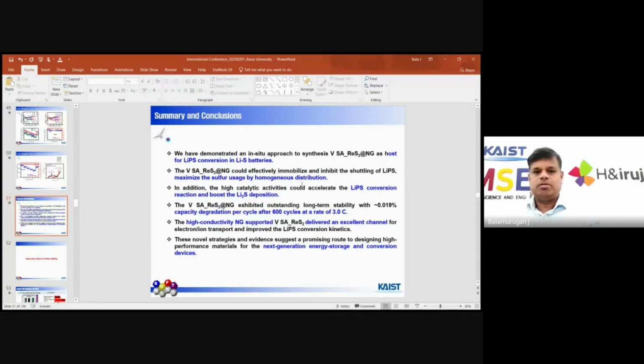So this is the conclusion. From the studies we can conclude that our catalyst gives higher catalytic activity for the lithium sulfur battery, and the cycling stability is very high. As I told you, regarding polysulfide conversions, we need to increase the polysulfide conversion, and enhance the kinetics towards the transportation of lithium from our single atom catalyst. Maybe it's helpful for next generation energy storage and conversion systems.